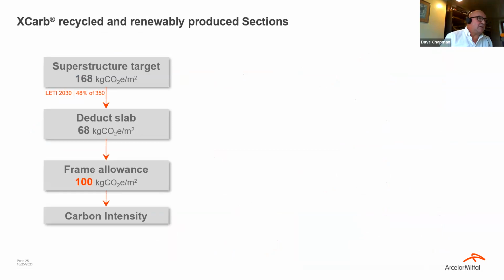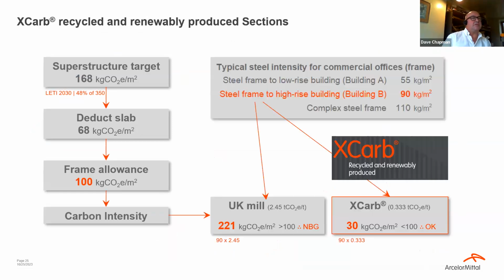You'd have to believe me, a similar sort of slab density for carbon of 68 leaves us with a frame allowance, whatever it is, of 100 kilograms. So considering our regular UK mills at 2.5 tons per ton of carbon, that amounts to 221 kilograms. So that isn't close enough. Whereas an X-carb alternative, as shown here, can amount to 30 kilograms carbon per meter squared. So it could still work. 2030 is coming. Next slide, please.